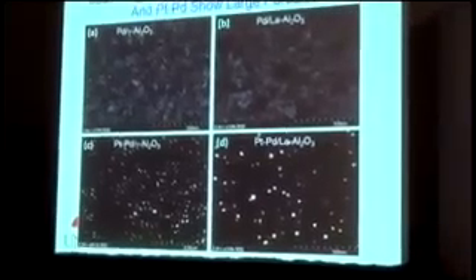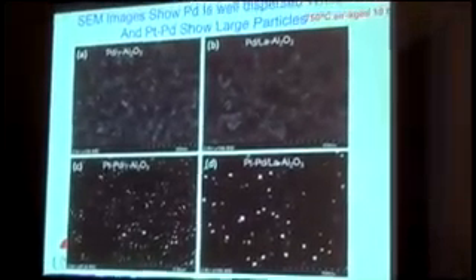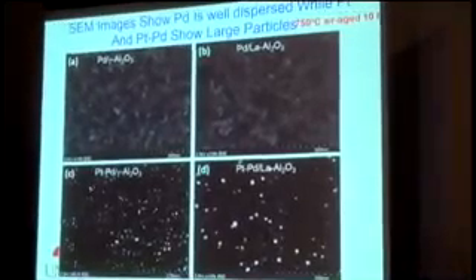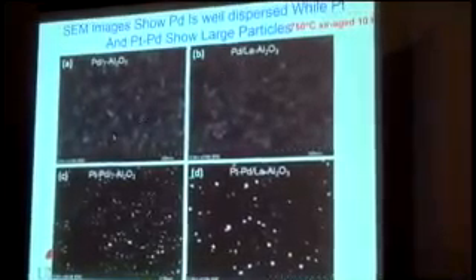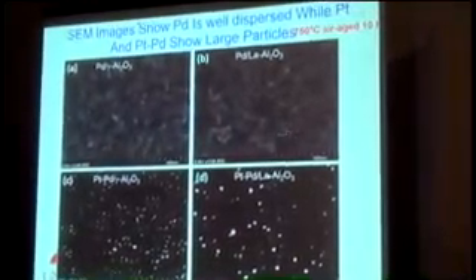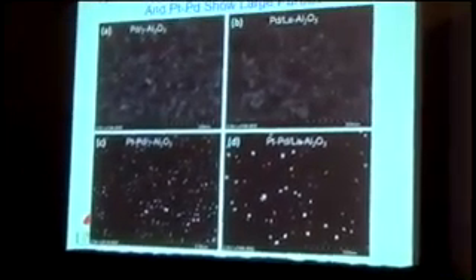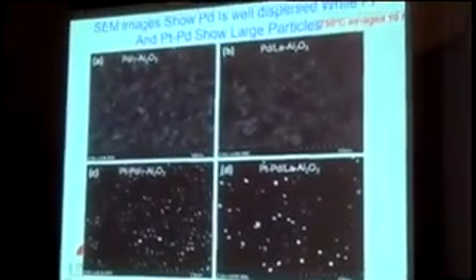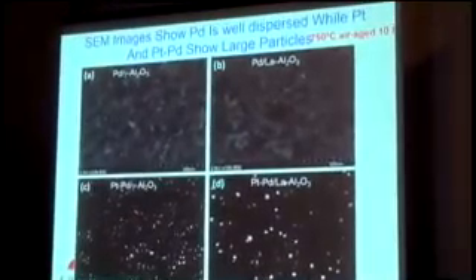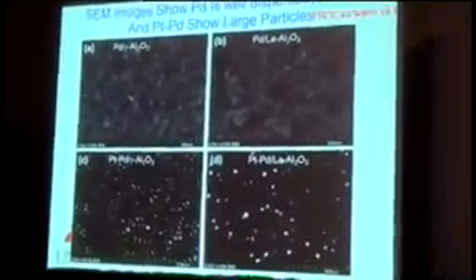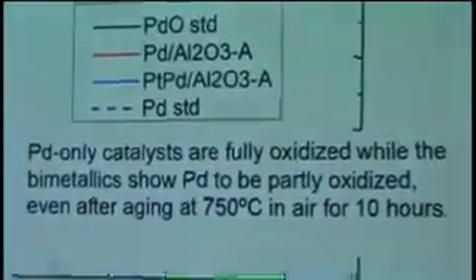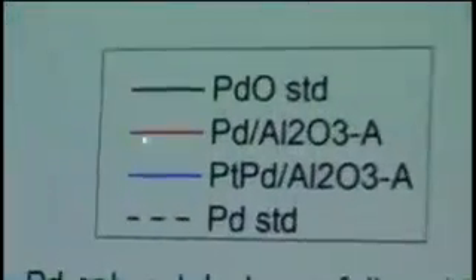So, your first conclusion, after looking at this, will say that platinum is inducing the sintering of palladium. Because palladium in air doesn't sinter at all. It forms an oxide that is not volatile. Platinum does sinter, and that's what's happening. The presence of platinum is keeping the palladium metallic, and it starts to sinter. Okay, we can prove this by XRD, so we know that if I just take palladium and alumina and age it in air, it's all oxide.